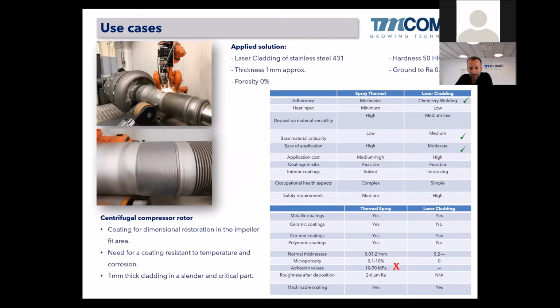Another example. In this case, we had to repair a centrifugal compressor rotor, specifically the fitting area of the first stage impeller. We have removed the first stage impeller. The impeller was very worn, and there was some corrosion underneath the fitting area of the impeller. So we had to machine about 1 millimeter of worn, very corroded material in this area. So we need a very tough, sound coating. So the best option here for us was to use the laser to apply a metallic coating.